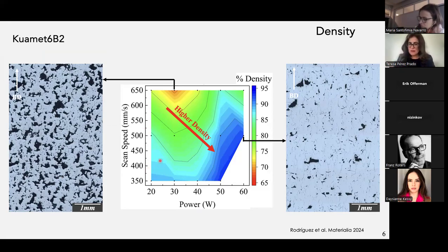This is a color map. I'm representing just the density. Within this small processing window, here we have the scan speed, here we have the power, and you see the density varies from like 65 to close to 95. Here we have two optical micrographs. These are cross sections parallel to the build direction, which is the perpendicular here, of two cubes. Even under the best conditions, you see that the quality is not very good, and there are all these very fine cracks that are parallel to the build direction. So this is not looking very good in terms of density.